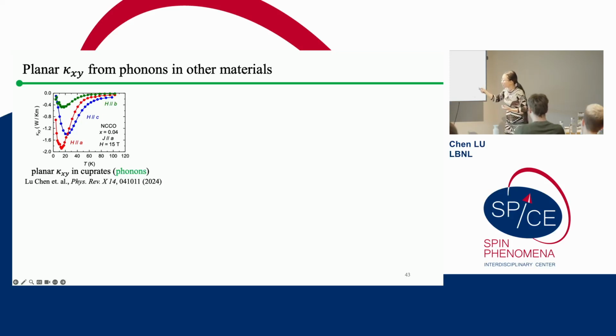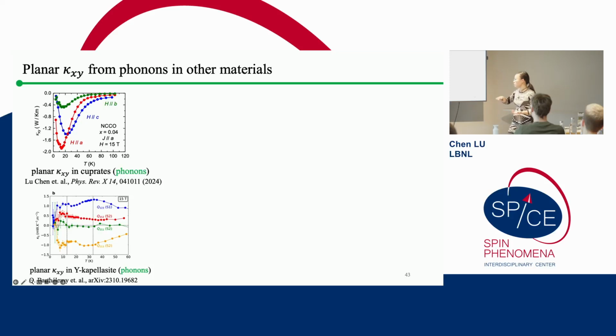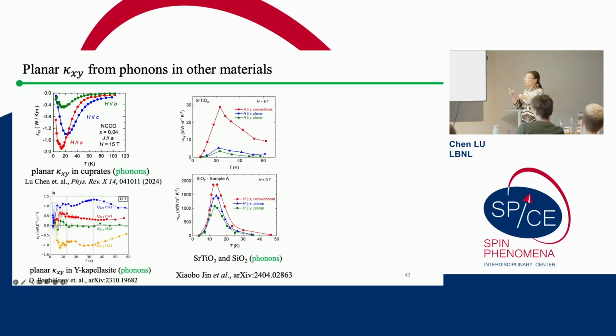We tried to measure the planar thermal Hall effect in different types of cuprate materials. What I show you here is in particular an electron-doped cuprate material, which is an insulating material, and we also saw a non-zero thermal Hall conductivity coming from phonons. Apart from that, my former colleague also studied this planar thermal Hall effect coming from phonons in another frustrated magnet system, the so-called Y-kapellasite. And we again saw a non-zero signal. So it means that this signal is probably something much more common, not only limited to the Kitaev system. Apart from our group, Professor Yuji Matsuda's group and the Huan's group, there are other groups trying to repeat this kind of result.